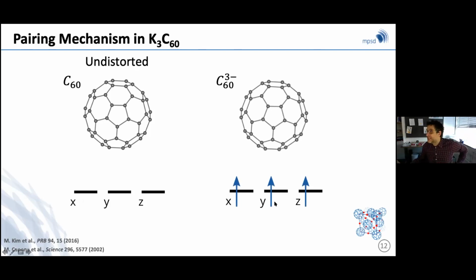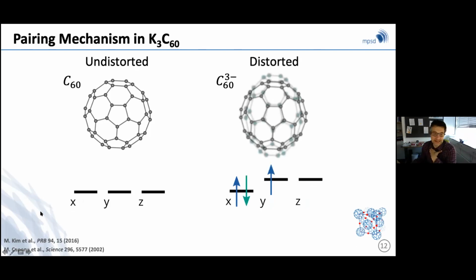And once I dope those to 0 order in an undistorted molecule, I expect these 3 electrons, because of Hund's rule, to occupy these orbitals in a high spin state, except that the molecule in this way is unstable against the Jahn-Teller distortion. And so the molecule distorts and creates a low spin state, which is an S=1/2 state.